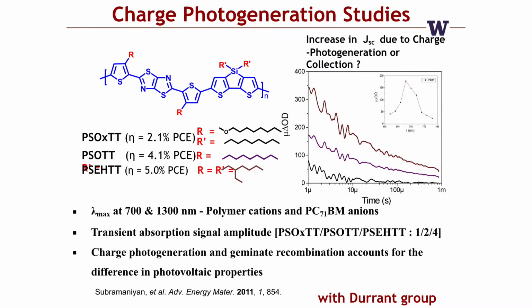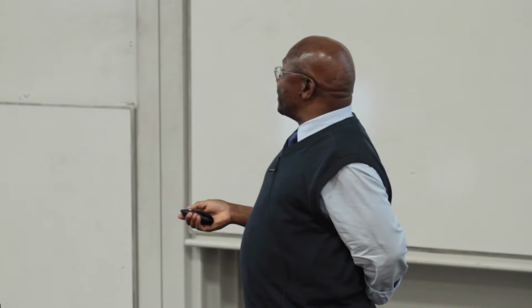could be one way of searching for polymers that are going to be able to pack in this way, because we do know that that kind of packing leads to better photovoltaic efficiency and better performance, as indicated here in a combination of charge photogeneration studies done in collaboration with the Durrant group here at Imperial, and devices that show that indeed PSEHTT among the three has better photovoltaic properties that can be clearly connected to this ability to pi stack in the face-on motif.